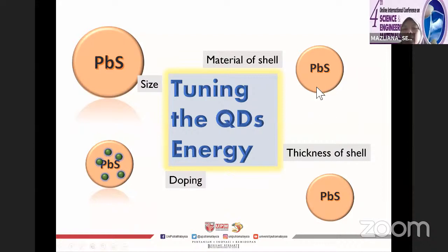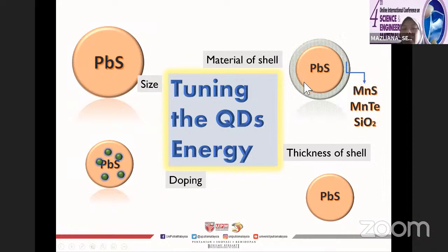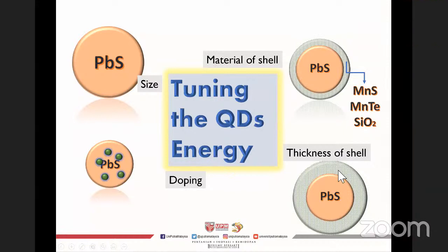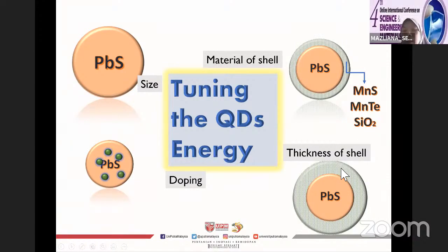We also can put a shell layer, so we can change the shell composition here. We can use manganese sulfide, we can use manganese telluride and so on. So the material of the shell will change the confinement of the quantum dots. And finally, we also can change the thickness of the shells. For example, if you already decided you would like to produce MnS core-shell quantum dots, you can change the thickness of the MnS shell layer in order to tune the quantum dots.